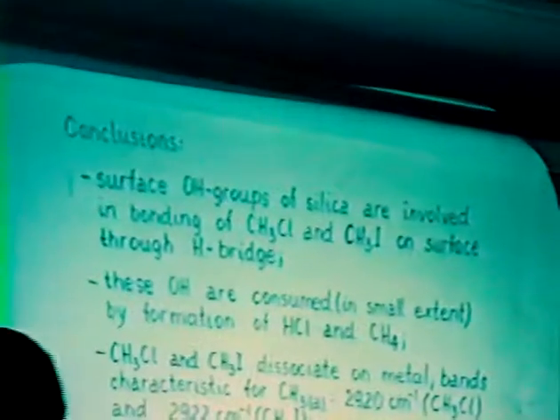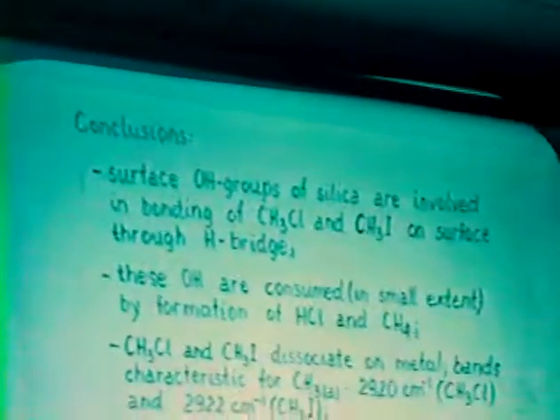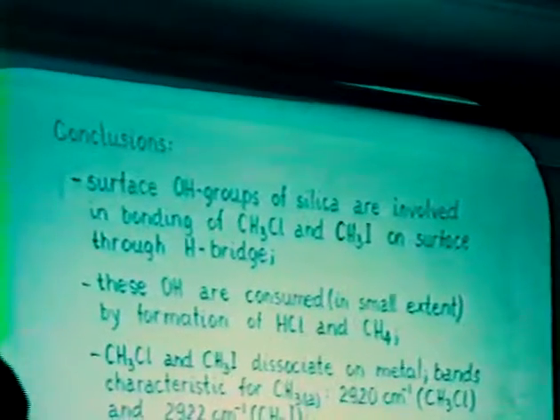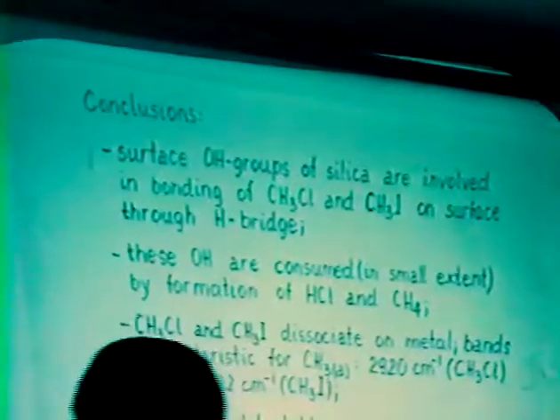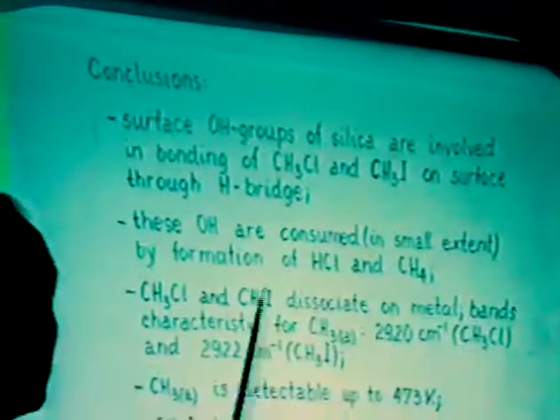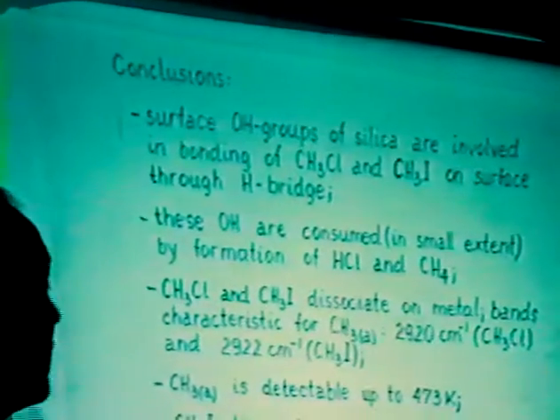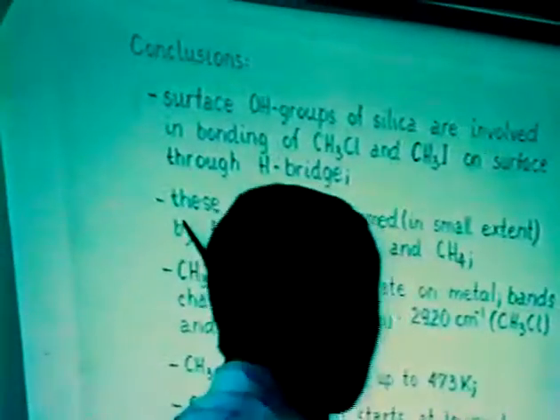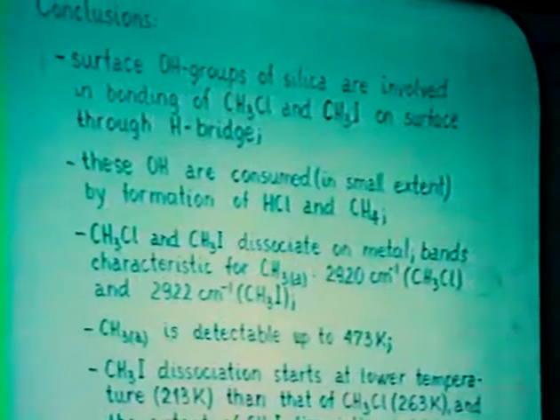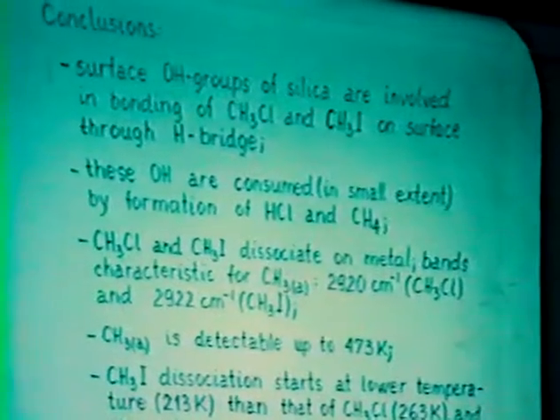And finally, may I summarize our conclusions here? We strongly believe that surface OH groups are involved in bonding of these alkyl halides on the surface through a hydrogen bonding, and these OH are consumed to a small extent by formation of hydrochloric acid and methane.